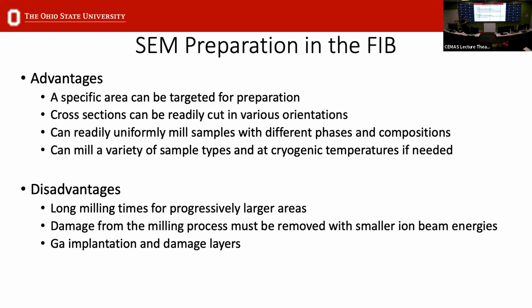In terms of disadvantages, the larger the area you want, especially in the case of the gallium FIB, the progressively longer it takes. If you were trying to mill an area 50 by 50 microns, that would take a very long time to FIB. And this can still introduce some damage that you must progressively remove with smaller ion beam energies. In addition, in the gallium FIB, you have gallium implantation that could interfere with some of your EDS analysis.